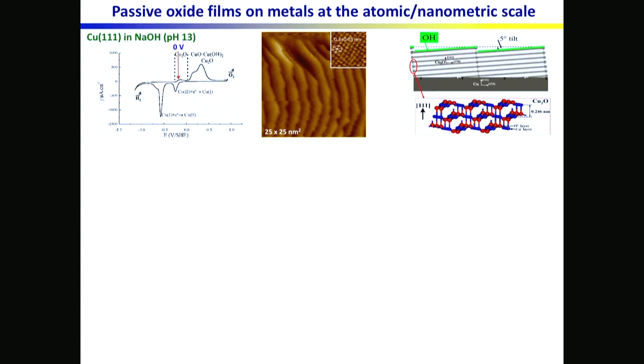However, as I pointed out, there are narrow terraces, and this means that the oxide is growing with a tilted angle between the orientation of the oxide and the orientation of the substrate. And by measuring the width and height of the terraces and height of the steps, which can be measured with a high precision using the scanning tunneling microscope, we can then get this model for the system with a smooth, flat copper 111 single crystal as a substrate, and the oxide is growing. So it is growing here in the 111 direction, but however, there is a tilt between the two, and the tilt angle can be deduced directly from these images, and it is 5 degrees.